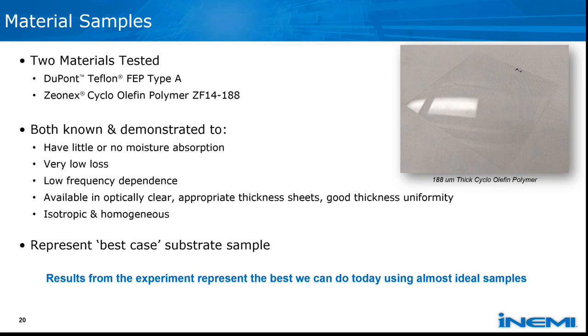They're also available in appropriate thicknesses. That turns out to be a problem for some materials because these methods have some limitations in the range of thicknesses. And so these two are available in sheet thicknesses that are applicable to these different methods. And they generally have good thickness uniformity. Not perfect, but very good relative to typical packaged substrate material samples that you can acquire. They're also isotropic and homogeneous.